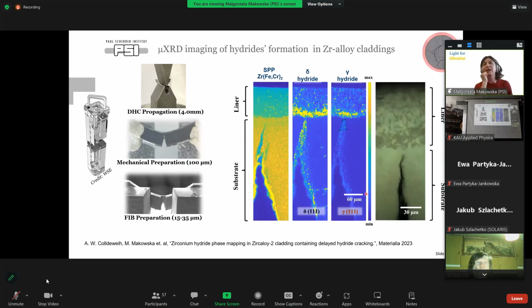So here, I would like to actually start with the 2D imaging. This is a thin lamella, also extracted using the FIB, of the cladding of the zircaloy, for which case we performed 2D imaging. So we were scanning in 2D over the area around the crack. So this is this crack in the zircaloy cladding, an on-purpose induced crack.